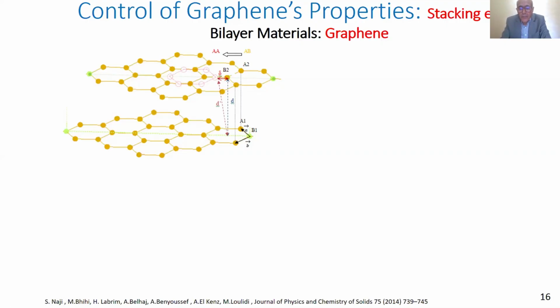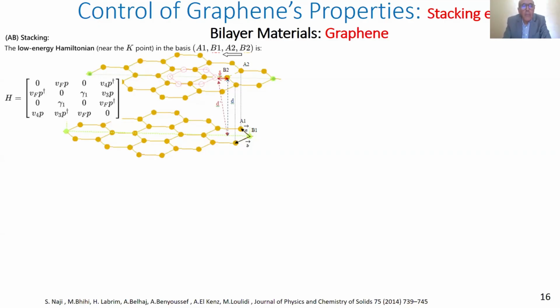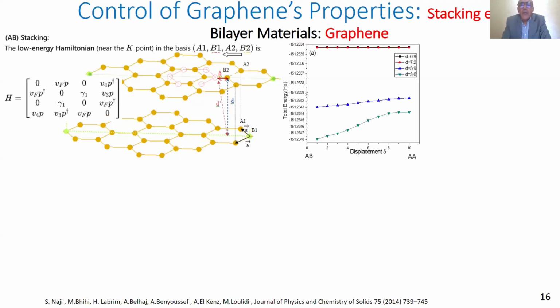But if we make a shift of this layer with respect to another layer, then we can change from AB to AA, where carbon is on the top of carbon. And what is shown here is the stability. We can see that the most stable configuration is AB, which has the lowest energy. Of course, it depends on the distance between layers. And if the distance between layers increases, then we obtain the behavior of graphene.